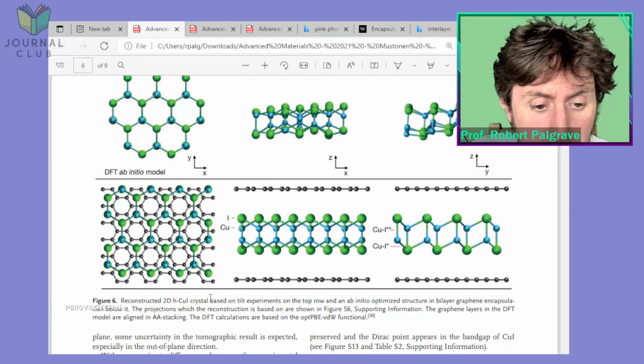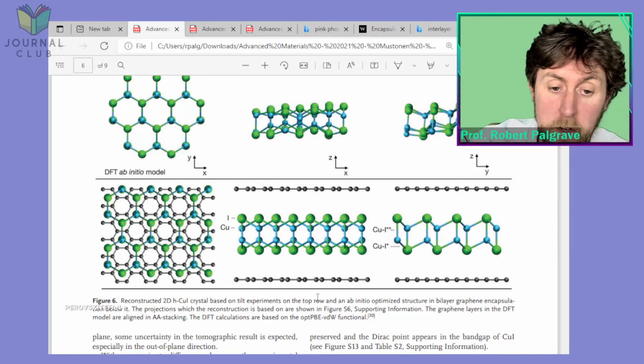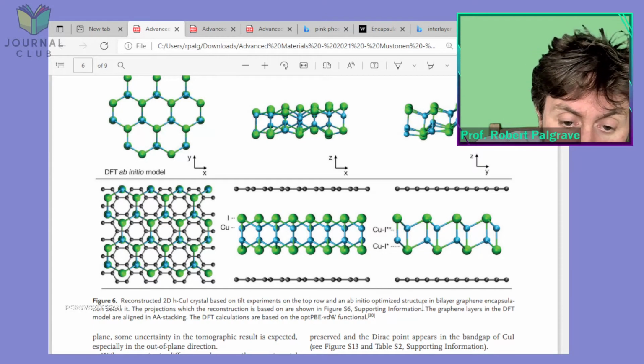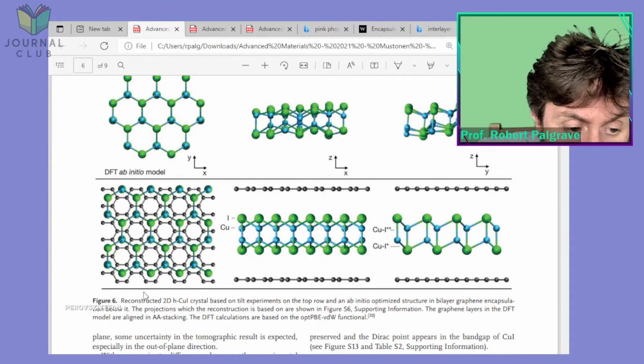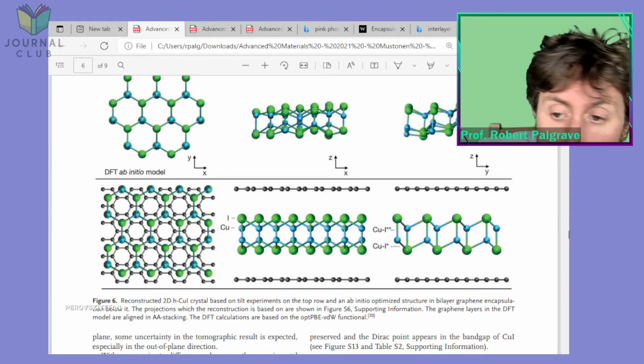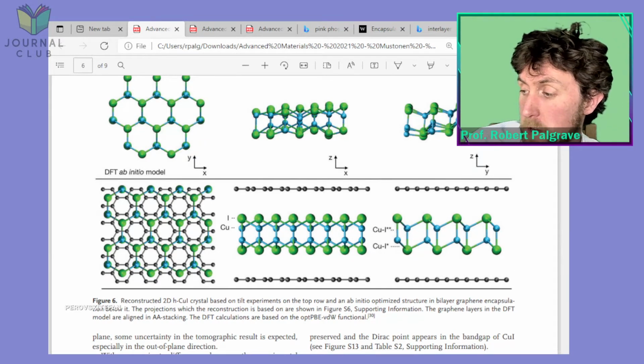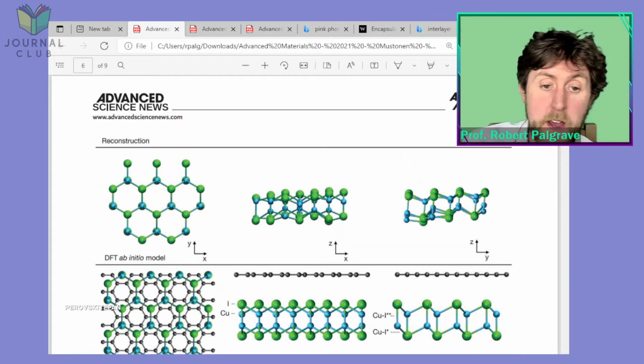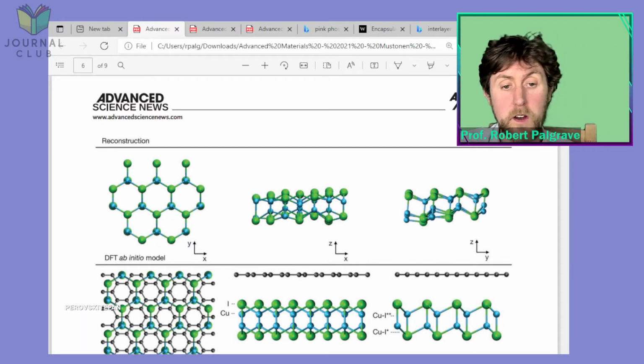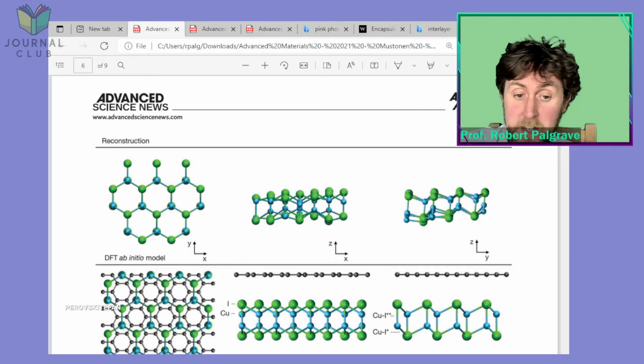Reconstructed hexagonal cuprous iodide crystal based on tilt experiments on the top row, and an ab initio optimized structure in the bilayer graphene encapsulated below it. Oh, right. Sorry, that's the wrong way around. Let me scroll up. Yes. Okay. So this is what they got from the TEM image, and this is the DFT.